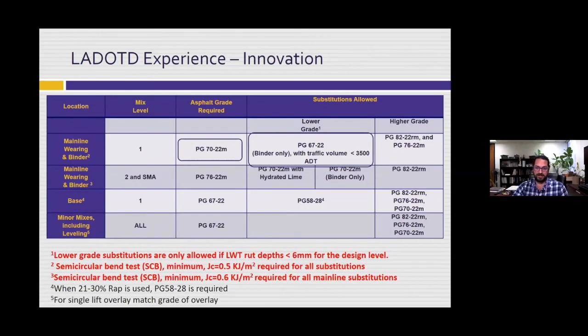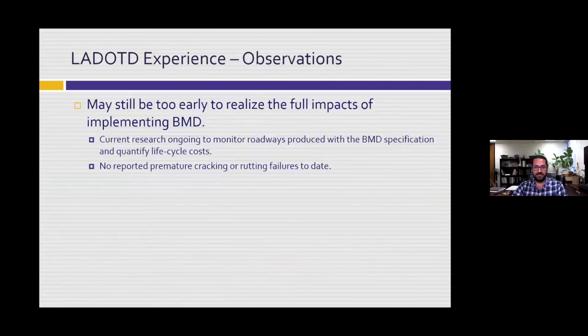Another thing we like about it is it allows innovation, both on the contractor and the state side. We allow binder substitutions for lower traffic roads as long as the LWT and the SCB criteria are met. Because again, at the end of the day, what we're looking for is a mixture that's going to not rut, not crack, be skid resistant, etc. It doesn't necessarily matter in the grand scheme of things what goes in it, as long as it performs in those key areas and lasts for 20 plus years. That's what we all hope. So having these tests allows for contractors to be innovative and being able to achieve those criteria and still be able to put this mixture down on the roadway.